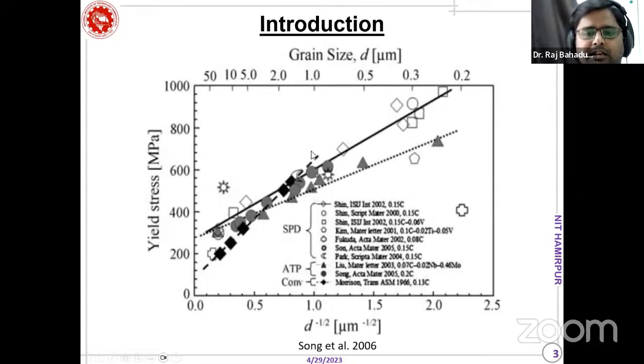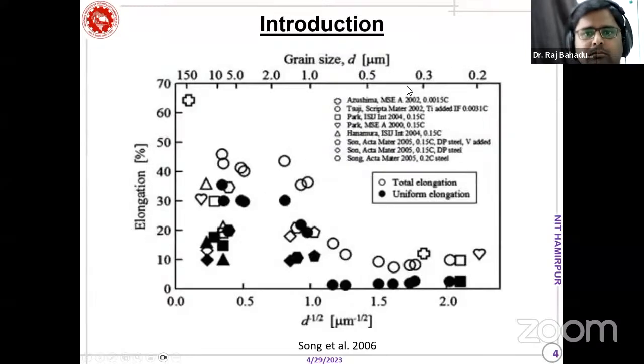Here the literature gives very crisp information. If the grain size is in the range of 0.2 to 0.5 micron, which is ultrafine grain, the strength is very high, around 1000 megapascal yield strength. And if you see the ductility or elongation of the material at that level, the ductility is very low; for 0.2 to 0.3 micron, the ductility is less than 10%.